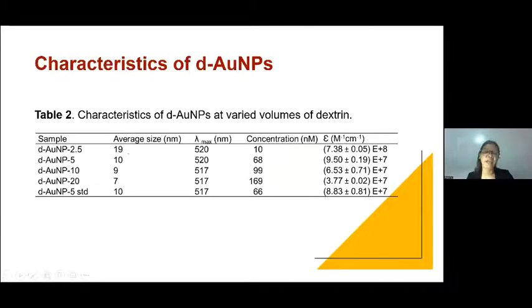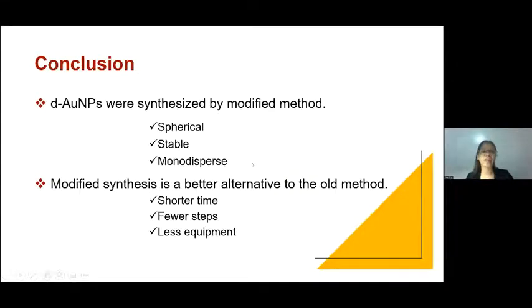You have the average sizes of 19, 10, 9, and 7 with different lambda max within 520 and 517, and the corresponding concentration. Therefore, it is concluded in this study that dextrin-capped gold nanoparticles were synthesized by modifying the original method. And these D gold nanoparticles were spherical, stable, and monodisperse. The significant reduction in time, accompanied by simplified procedure and equipment, makes the modified protocol a better or practical alternative to the old one.